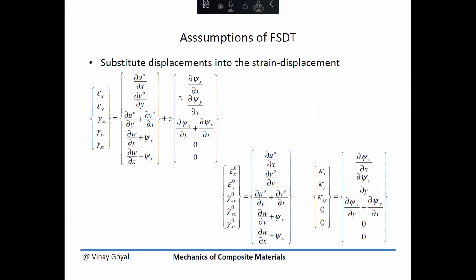If I were to put this into a matrix format, which is very convenient, we will find an expression such as this one. 5 components of strains that fully describe the strain field through the whole thickness of the composite is equal to mid-surface strains, plus we also have these 2 here, which are the shear strains and are the same everywhere through the thickness, plus Z times these quantities here. And I want you to notice how these terms can be put in here, and these terms can be put in here. And these terms correspond to the curvature of the plate. These 3 quantities correspond to the in-plane strains in the mid-surface. And then these 2 quantities represent the transverse shear strains.